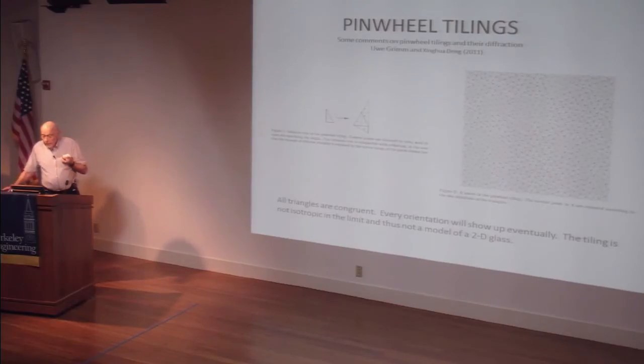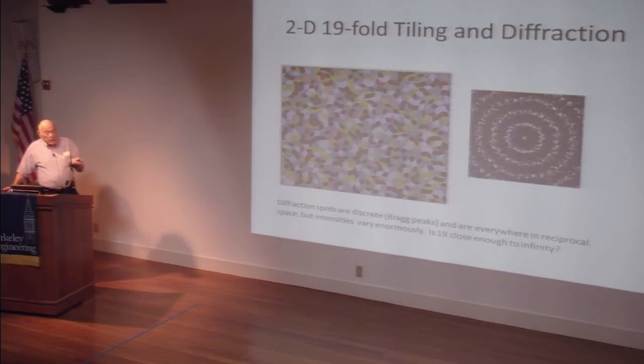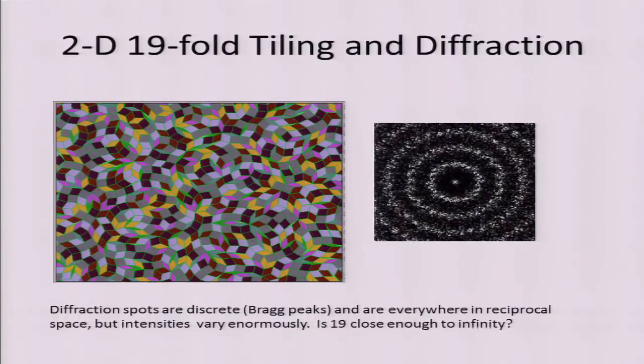And this has been known to the mathematician. Here is a pinwheel tiling, which is more or less isotropic. Every orientation exists in this tiling. It's made by taking a triangle, subdividing it into 5 triangles, then subdividing each of these into 5 more triangles, and eventually you make an isotropic mess. There are now computer programs for making Penrose tilings, and here's one which I did with 19-fold tilings, and that's the diffraction pattern.